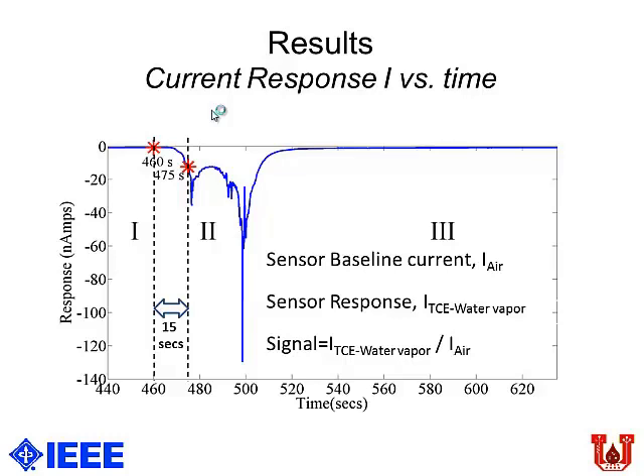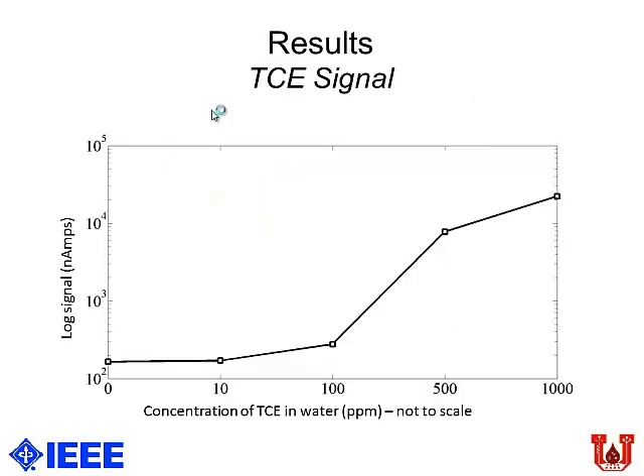Your actual signal is a ratio of your sensor response when TCE water is introduced to your sensor baseline current when there's just air. So that's a TCE signal. That's your 0 ppm, parts per million, which is, we don't have any, just bare water passed over the sensor. It has a slightly higher signal at 10 ppm and 100 ppm. It can detect from 1000 to 10 ppm. We tried higher than 1000 ppm, and we weren't getting a higher signal, and I kind of proposed a mechanism by which we think it doesn't work for very high concentrations of TCE.